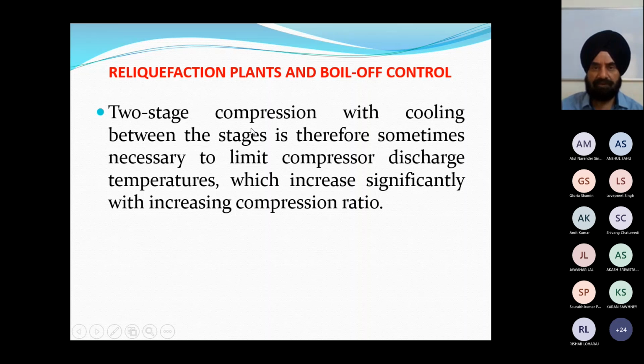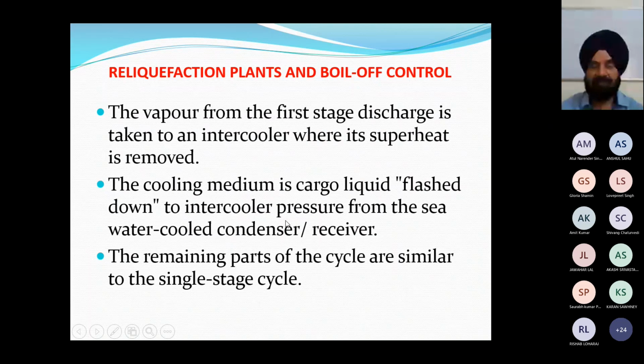Two-stage compression with cooling between the stages is sometimes necessary to limit compressor discharge temperatures, which increase significantly with increasing compression ratios. Vapor from the first stage discharge is taken to an intercooler where its superheat is removed, and then it goes to the second stage. The cooling medium is cargo liquid in the intercooler, flashed down to intercooler pressure from the seawater cooled condenser, and the remaining parts of the cycle are similar to the single stage.